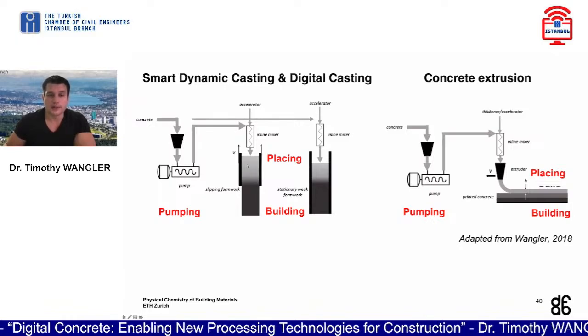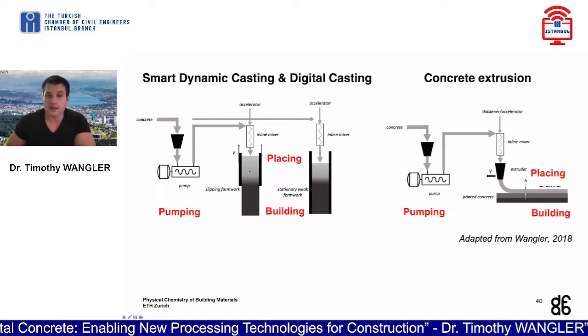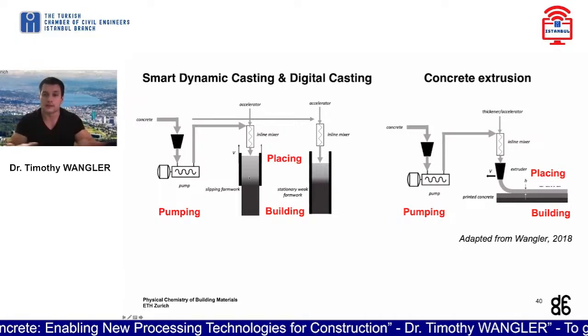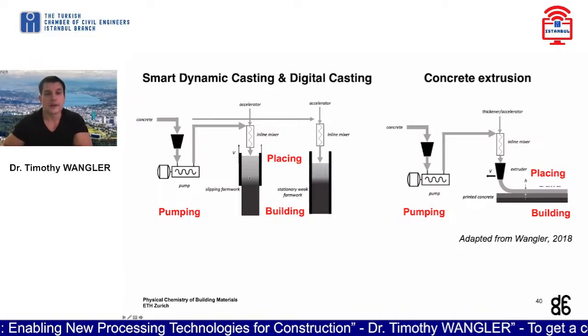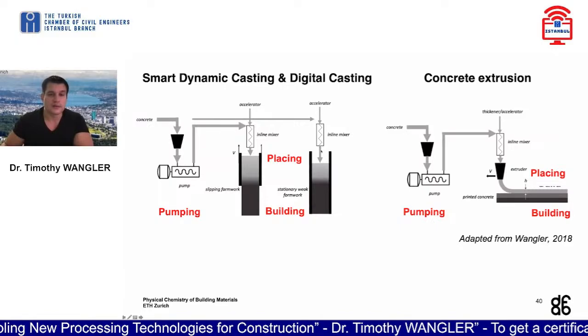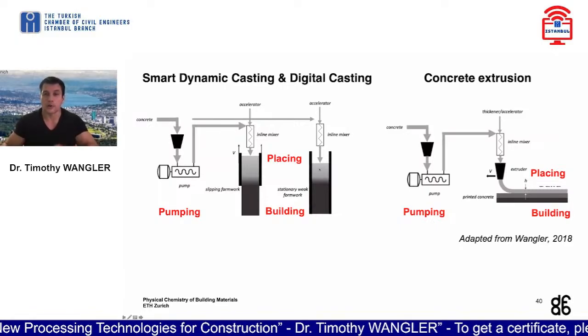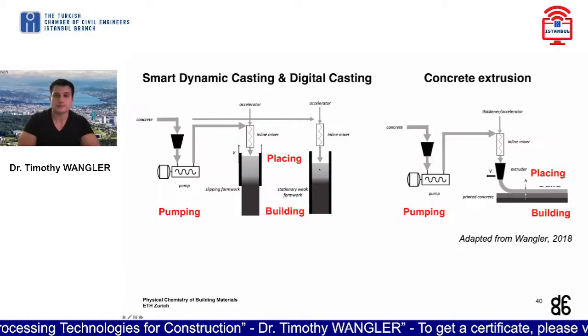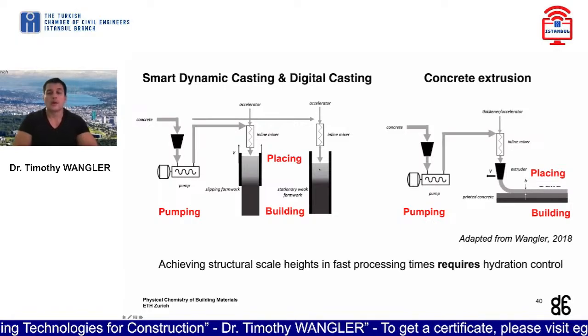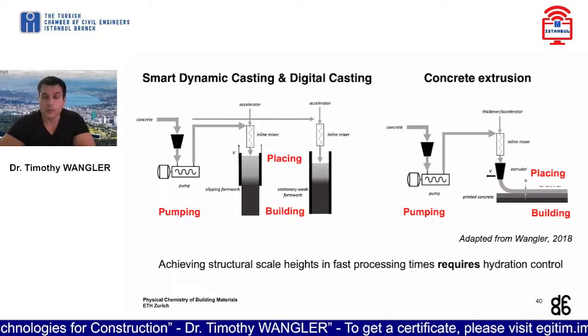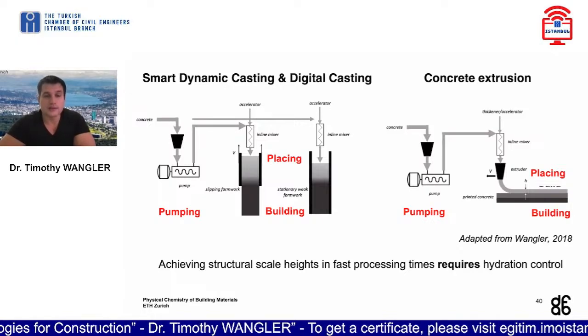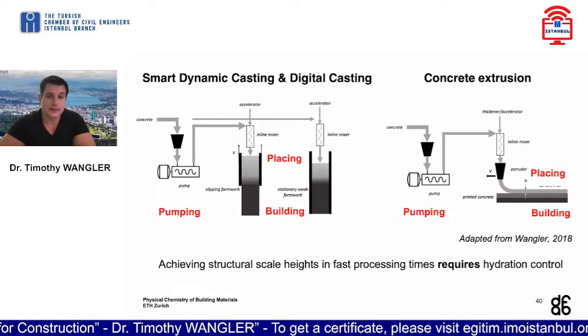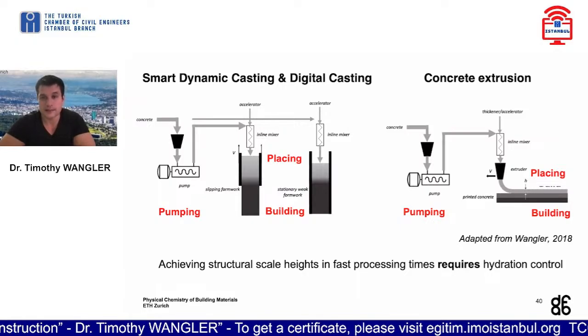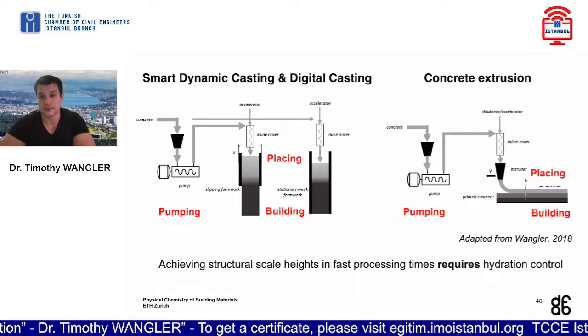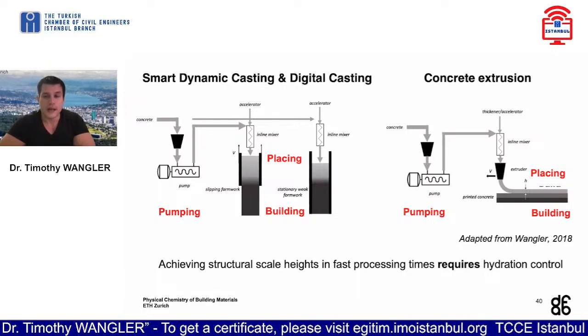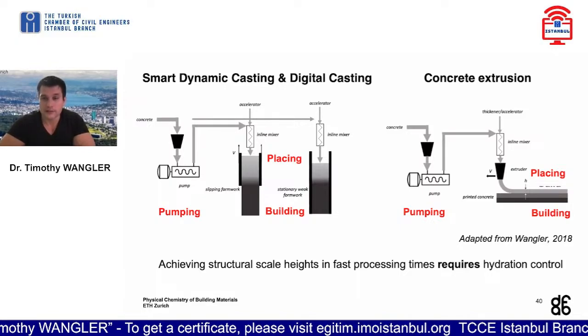You can put the concrete in, and then it has to harden, because as the formwork slips up, it just collapses if it doesn't come out. And in the case also of digital casting, the formwork will break. What we state is that if you want to achieve structural scale heights in very fast processing times, let's say you want to 3D print a building in 24 hours, for example, you have to have absolutely some form of hydration control.